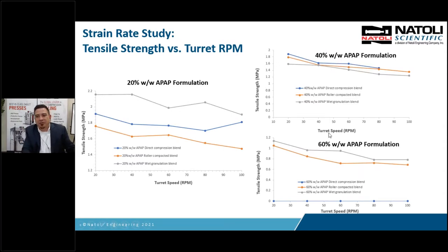Okay, take a look at the 40% APAP. Same thing, tablet strength versus turret speed. It is dropping. It's not a huge drop. It's not a very significant drop, but there is a drop. So you would expect when you go to a higher speed press that you're going to have to increase some of that pressure to get to that strength you want. And remember, on a tabletability curve, if you're up at that plateau area and you got to add more pressure because of the higher speed, well, now you might be capping. So that's why it's so important to know where you are in that curve.